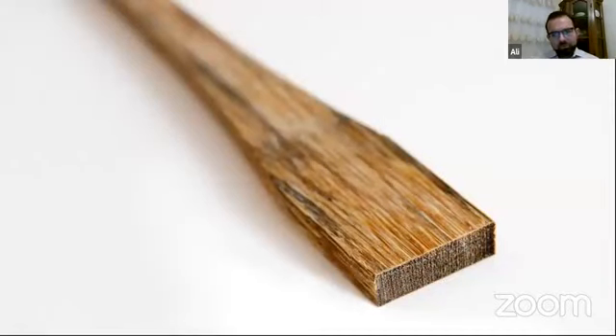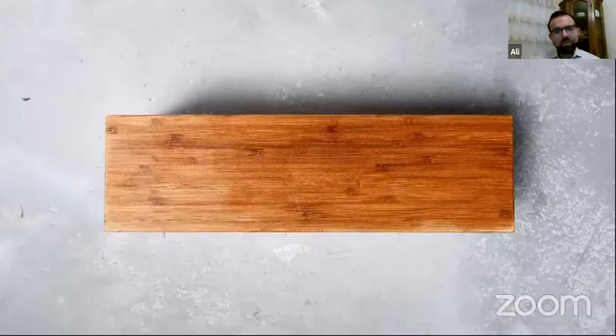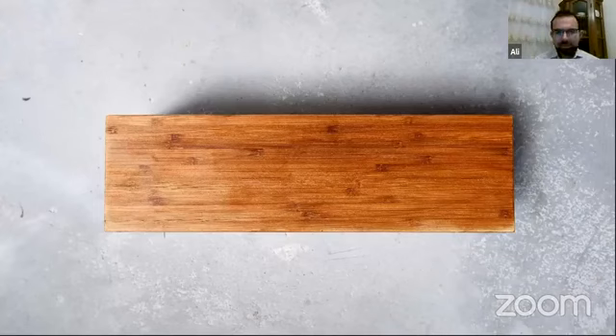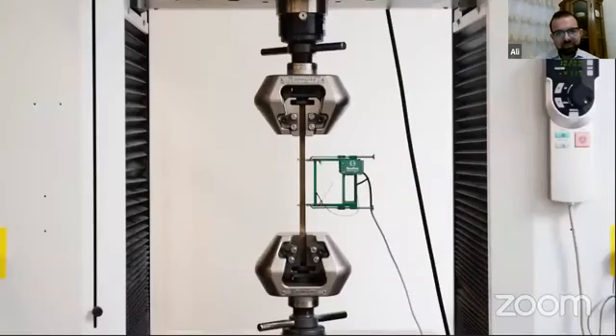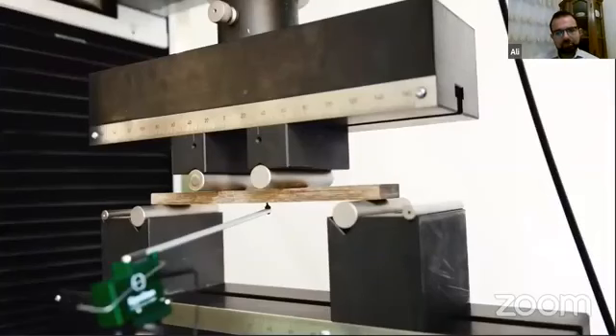So I will just go through some of the pictures of the samples that we produced. These are samples that we used for pull-out tests for use in concrete. This is a sample that we used for making a house in Indonesia that I will show later on. Again, regularly we had to do testing of mechanical properties like tensile strength and elastic modulus, in terms of tensile along the fibers and across the fibers. Again, bending along the fibers and across the fibers, and elastic modulus.